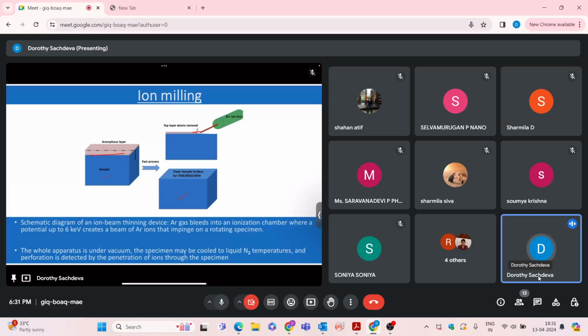So this argon gas bleeds into an ionization chamber where a potential up to 6 kiloelectron volts creates a beam of argon ions that impinge on a rotating specimen. The whole apparatus is under vacuum. The specimen may be cooled to liquid nitrogen temperature, and perforation is detected by the penetration of ions through the specimen. So you can have your rotating disc where you can place your specimen, and then these ion guns are bombarded on this surface, and this whole instrument is under vacuum and at liquid nitrogen temperature. So then you can thin your specimen using this ion milling technique.